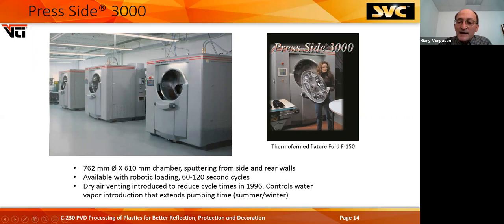The right-hand picture, you can see a thermoform fixture. This actually is a polycarbonate fixture for F-150 taillights. They snap into the backside. There's a mild steel washer here on the front, and the fixture is just held in the machine with a magnetic coupler. So it's easy to snap the parts into this. This fixture sold for about $300, and it had a useful production cycle of about 1 year.